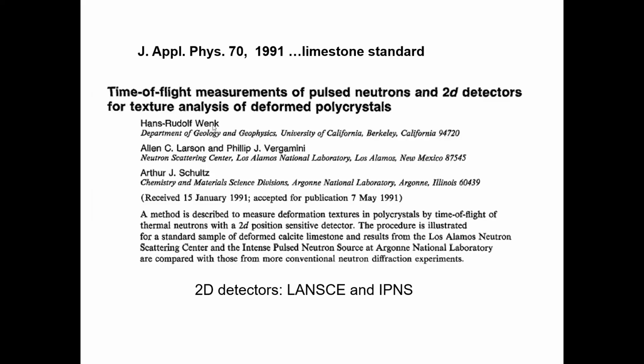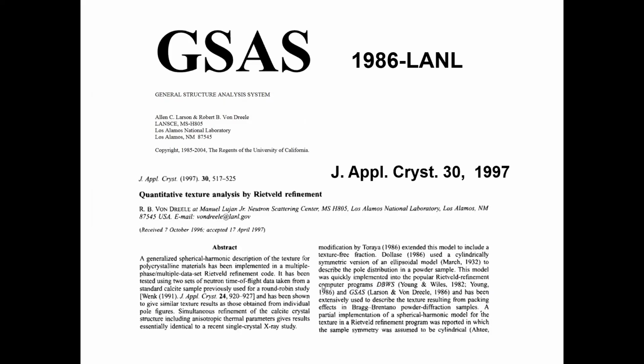We measured this both at LANL and at Argonne with Art Schultz, here with Al Larson, and the results were very convincing. In fact, 1986 was an important time for Bob and Al, where they came out with the first version of GSAS, which has since been used by thousands of neutron diffraction experimentalists to process data.